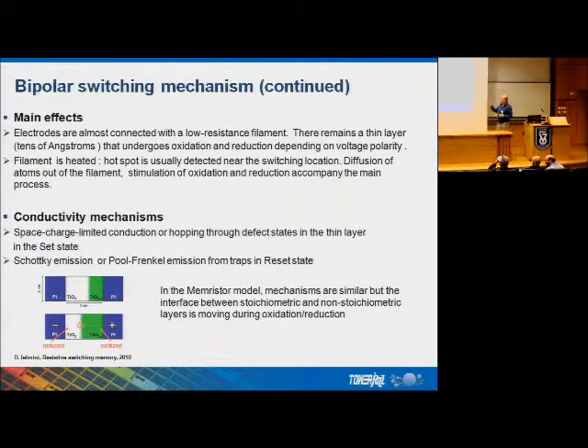Now, just to summarize what was said, so the main effects in the switching are connected with reduction, oxidation near one of the electrodes, and the area, the volume of this area where this process happens is only tens of angstroms. It's necessary to understand that in this area near the electrode, the densities of current are very high. So thermal effects are inevitably included in operation of the device. And this is not good. If these thermal effects are on purpose controlled in phase change memories, here the control is possible to much less extent. So most of the models of oxidation, reduction, they need to take into account not only the chemistry, but also the chemistry plus thermal effects.